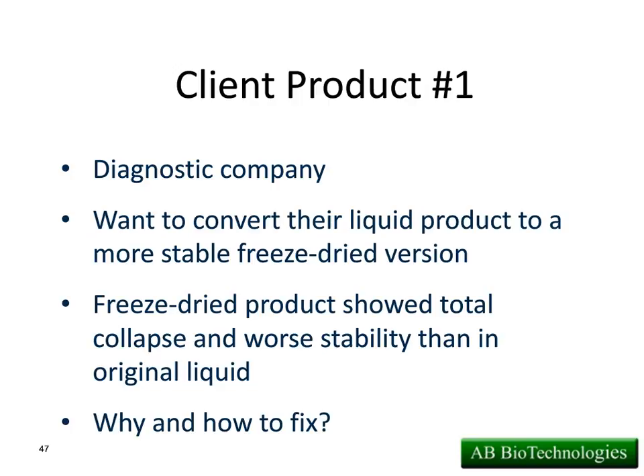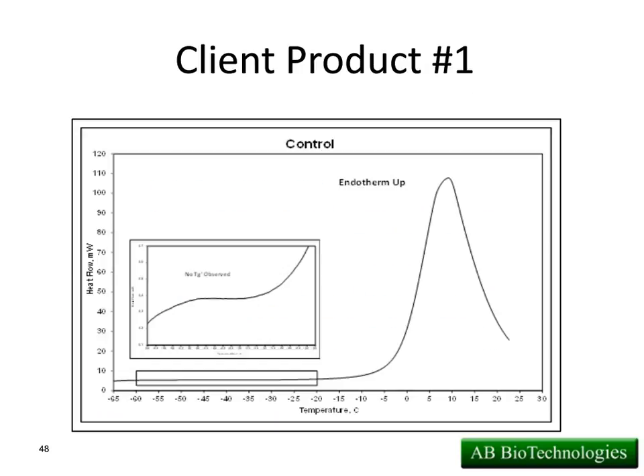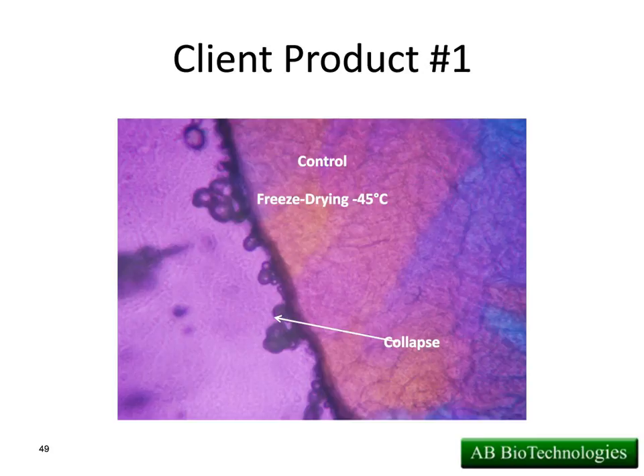So we went through and did some analysis. What we found is that their product had an extremely low glass transition temperature, to the point where we couldn't even freeze-dry it, okay? In this particular case, the glass transition temperature, we didn't even observe it, so we couldn't even get low enough. In this sample, we only went down to negative 65. We couldn't get low enough. So what we ended up doing, again, this is the freeze-dry microscopy. This is freeze-drying at negative 45. Again, we can't retain image. So we know the glass transition temperature is somewhere below negative 65. We didn't even see it in the DSC.